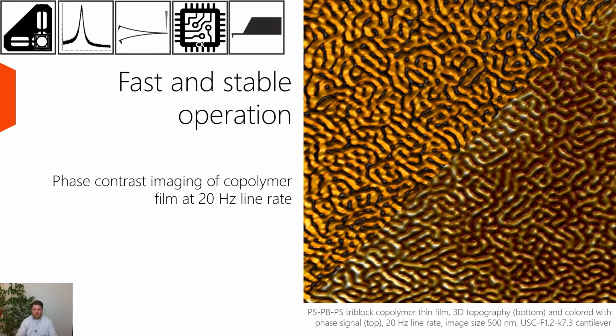Fast and stable operation are also very important for AFM, especially if you want to image a lot of samples. Fast operation is a benefit. What you see here is an image of a copolymer imaged in phase contrast. You see a phase signal up here and a topography signal down here, at a line rate of 20 Hz with the DriveAFM. This image was taken in air, and here the small cantilevers come into play, because they have a higher bandwidth, and just using regular cantilevers at a few hertz of line rate, their response would be too slow to properly track the surface and give you a proper topography.